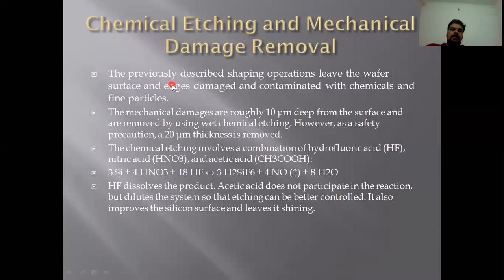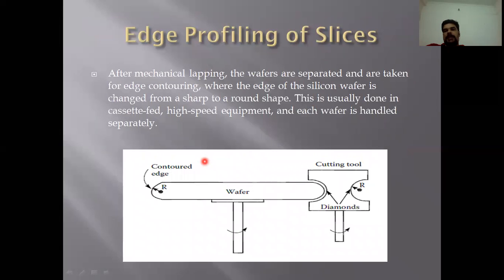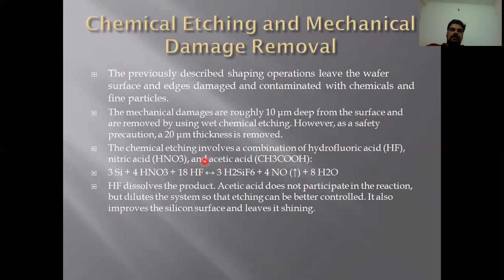So this is the chemical part. After that, chemical etching and mechanical damage removal is done. The previously described shaping operations leave the wafer surface and edges damaged and contaminated with chemicals and fine particles. All the previous methods were basically mechanical operations performed on the silicon ingots to get silicon wafers, and by these mechanical processes there were several damages and contamination on the surface. Certain chemicals can also contaminate the surface of the wafer.